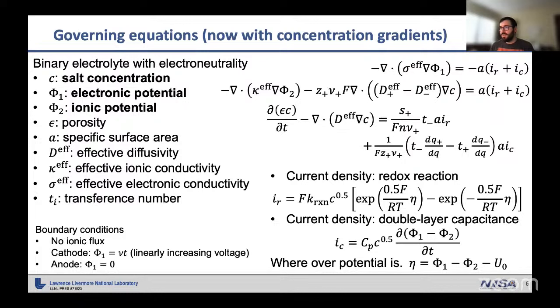So there is migration of the ions due to the ionic potential, but it's written in this weird way because we chose the salt concentration. This is like the classic battery model where you ignore diffusion inside particles. And we also wanted to look at supercapacitive storage. So we have two reaction terms, redox and double layer capacitance. I'm not going to go through all these details, but these are two types of storage. Redox is for a pure battery, and then capacitive would be for a pure capacitor, supercapacitor. If you have both, then you're a supercapacitor.